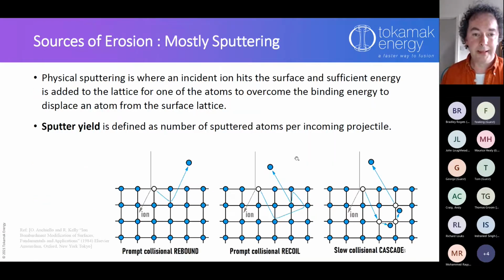I've got a bit more on sputtering here. What's happening in sputtering is that ions are coming down and they're hitting the surface. The surface is made up of a lattice. This is a metal, could be steel, could be something else. And there are various different mechanisms, but this one, for example: the ion hits this atom, which has been nicely bound in the lattice, and gives it enough energy to escape its binding energy. It flies around a bit, repels off, and rebounds out of the surface. So this atom then flies away. There's a whole bunch of other ones as well, with cascades and all sorts of other things.